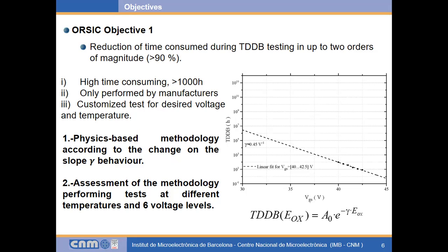And we can see that the TDDB at 30 volts should be around 10 million hours. But what happens if we would like to make the test faster? At one point, the acceleration factor of the thermochemical model changes. Then this could lead to an overestimation of the lifetime.